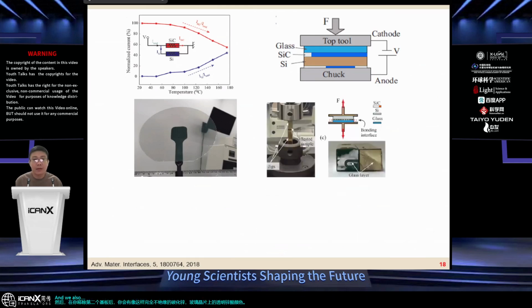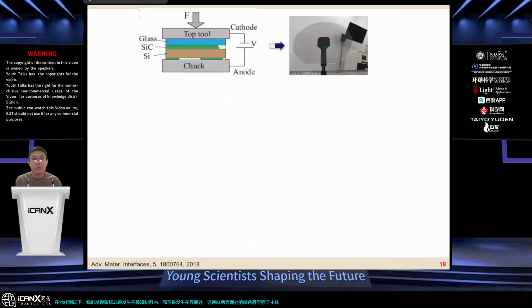And we also collaborate with the University of Tokyo to explore its bonding strength. Under the pulling test, we found that the crack always happened within the glass material, but not at the interface, meaning the bonding at the interface is even stronger than the bulk glass substrate. And before we optimized the bonding conditions like pressure and surface treatment to obtain a good bonding between silicon carbide and glass, we experienced a lot of failure.